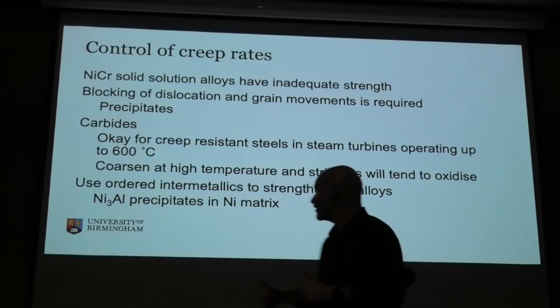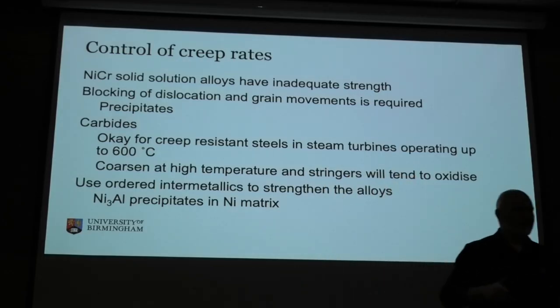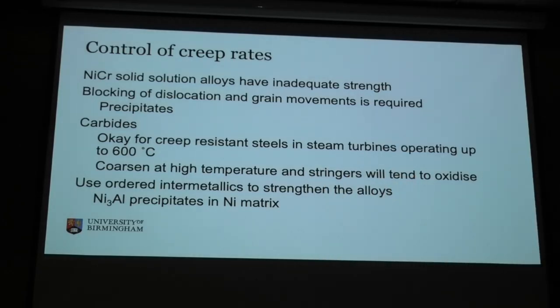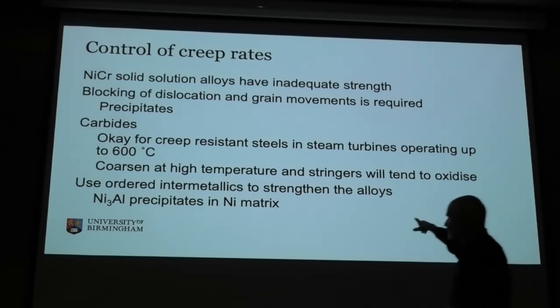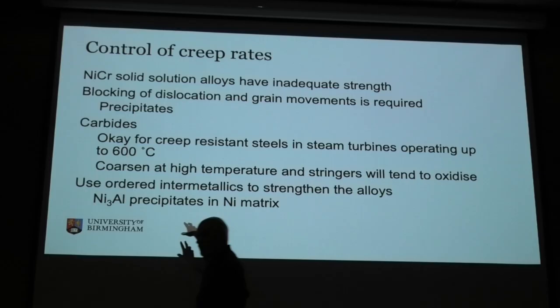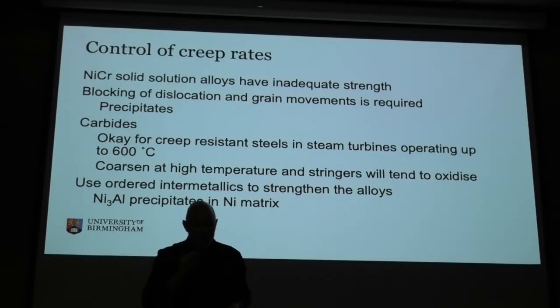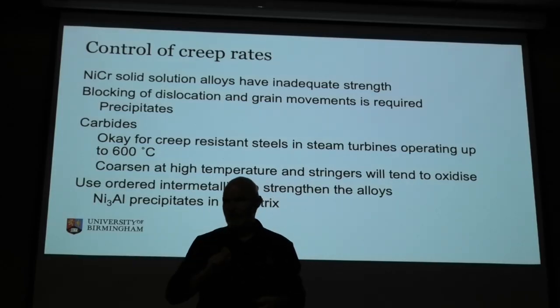Really, really good. Unfortunately, you go over about 600 degrees C and those carbides start to coarsen, at which point you lose strength. So we're kind of limited - we're a few hundred degrees C above where that actually works for us. So we actually use a nickel aluminium alloy and we get little precipitates that we can control at the right temperature.